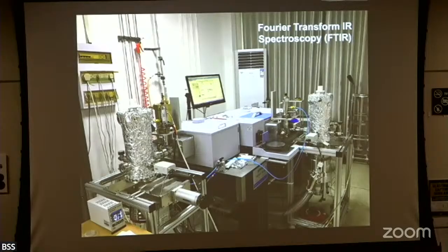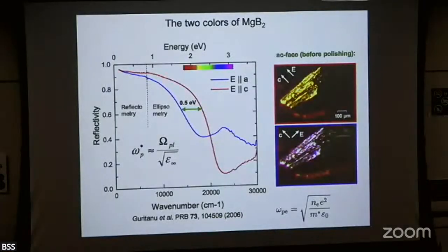The frequency ranges that one measures here, let me show you, I'll go two slides down. This is an example of a sample. This is on magnesium diboride, the highest TC conventional superconductor. In an experiment like this, we measure the reflectivity as a function of frequency. And here you see these terrible units, wave numbers. What's a wave number? Remember from my plot, 10 wave numbers is about 10 degrees Kelvin, which is about 1 meV, which is about 200 gigahertz. So a wave number is about a degree, that's an easy thing to remember. This is something of order about 3 electron volts here.